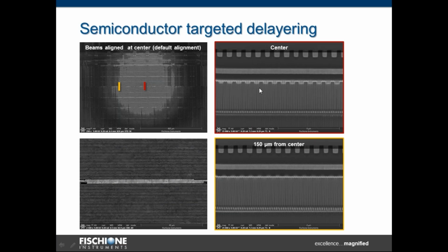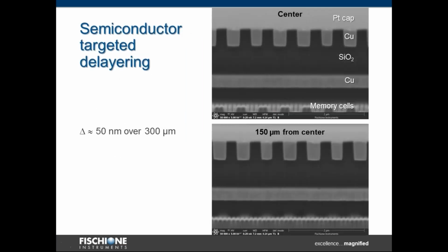Another question is, how uniform is that delayering? So we did a cross-section, FIB cross-section in the center, one in the extreme of the milling area. As you can see here, the cross-section, one in the center and another one 150 microns from the center. So you can see the cross-section are very uniform, very similar. And if you look closer, you will find the uniformity of the milling is 50 nanometers over 300 microns. So it's very nice and clean, the target delayering process.